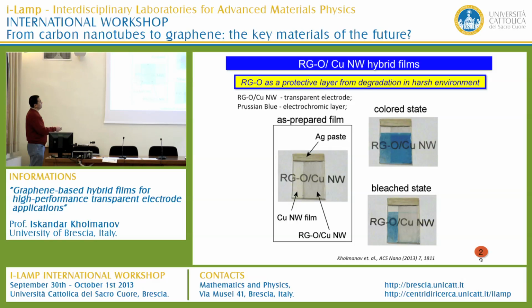And in the next step, we tried to use it as an electrochromic device. So we tried to bleach the Prussian blue film. As you see, the Prussian blue only on top of the hybrid film area is bleached. So this area works as a transparent electrode, but this area cannot work because here is pure copper nanowire film that reacts very strongly with Prussian blue and forms a copper iron cyanide complex. The reaction of Prussian blue with copper nanowire completely destroys the copper nanowires and the percolated network of copper nanowires.